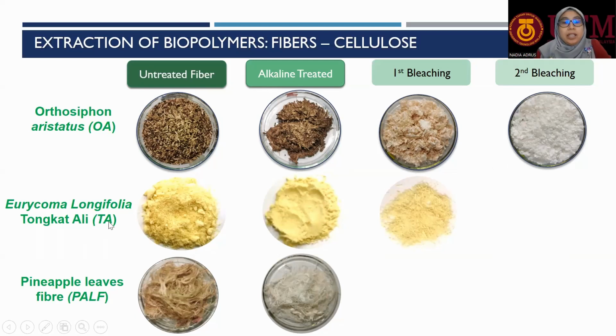For tongkat ali, TA, we subjected the fiber to alkaline treatment and first bleaching. And for pineapple fiber, the fiber was only subjected to alkaline treatment. Since pineapple fiber contains a high amount of cellulose and less lignin, it is not necessary to continue with bleaching, as it already gives you a fluffier structure after alkaline treatment. But in the case of OA, you need 2 times of bleaching, and no further study was done for tongkat ali, which is TA. So here we can conclude that different cellulose needs different purification methods.